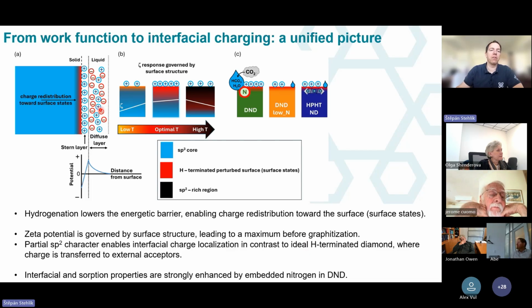when we measure the zeta potential, we always measure somewhere at this slipping plane, right? So we don't measure the neat particles, but particles with some hydration shell. Otherwise, we would not have a stable colloid. And we saw that the HPHT nanodiamond also has some water on it. So we suppose that there must be some hydration shell, and the kind of ions which can cause the positive zeta potential are these hydronium ions. So this for us is the most plausible explanation. But it's also modulated by the surface chemistry.